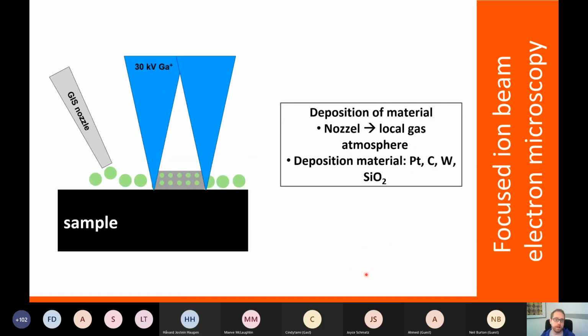So we can not only image and cut into the material, we can also deposit other types of material. So if we have what's called a gas injection system, we can actually inject gases, and typically this is platinum, carbon, or tungsten gases into the material, and with the ion beam we can steer the material to deposit specific layers.